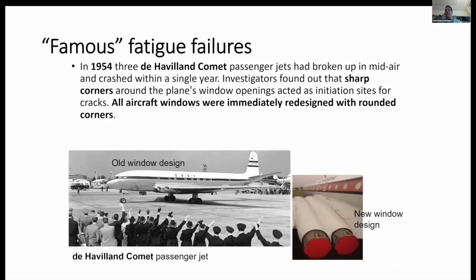We also have this very famous fatigue failure, which is probably the first passenger jet in 1954, the de Havilland Comet. And there, the problem was exactly the design of the windows. The windows were rectangular, and in the corner of the window there was a crack that was propagating, because the airplane acts as a pressure vessel. So it pressurized and depressurized. So we have stresses at the cell of the airplane. And because of this failure and the post-mortem investigations, the new window frame of this airplane was circular, and now we have these windows that you've seen in airplanes. So the message here is that if you see an airplane with rectangular windows, take the next one.